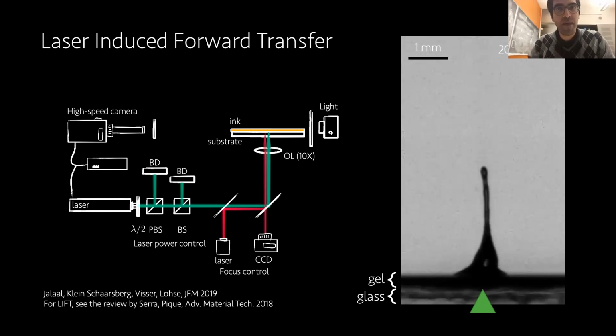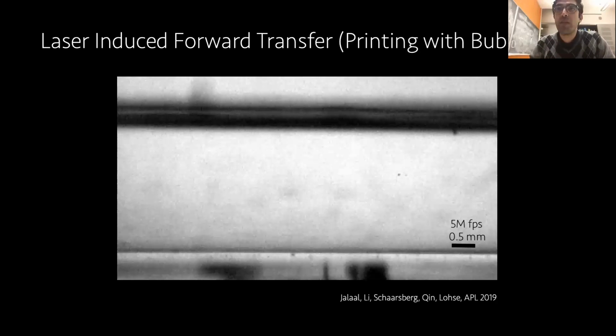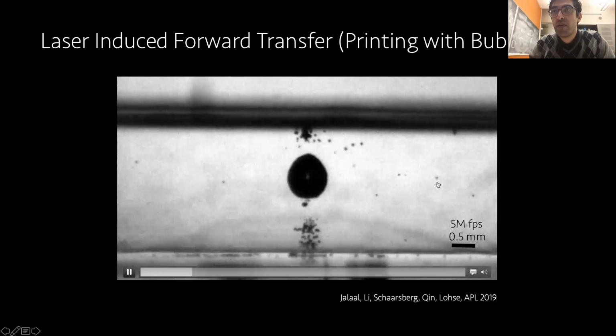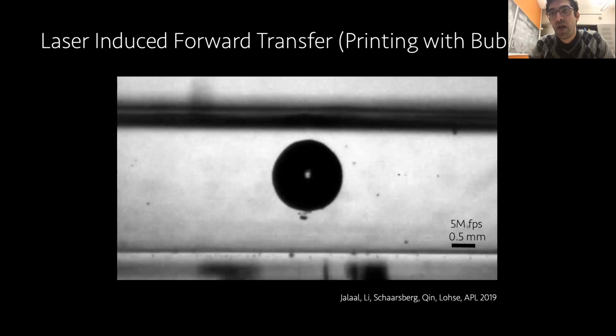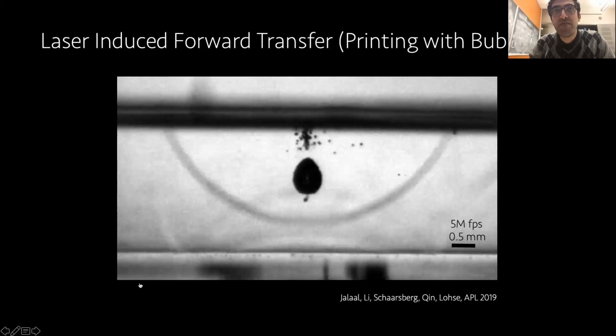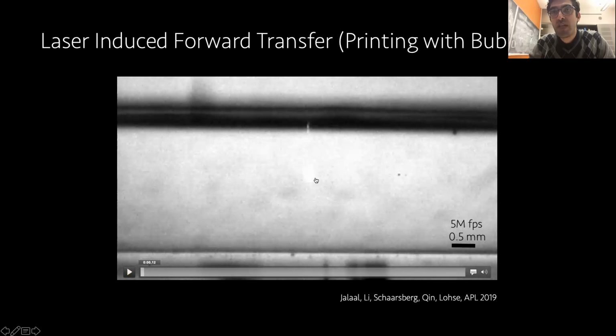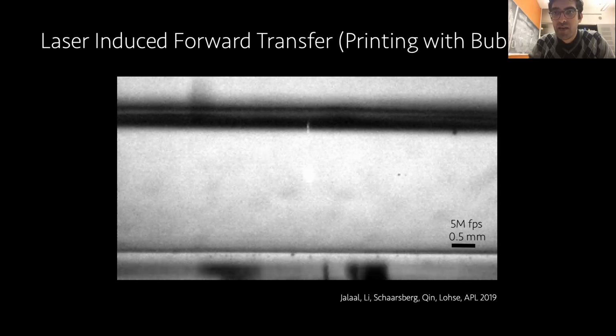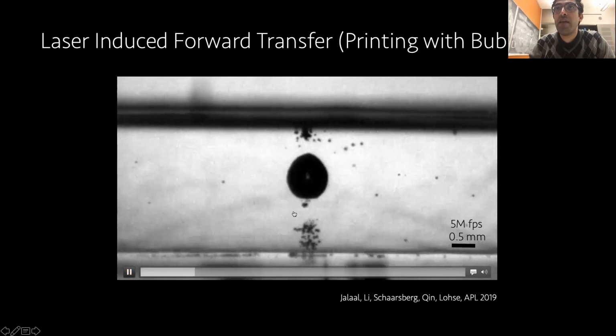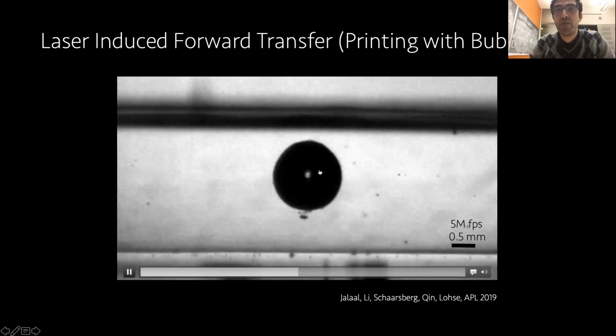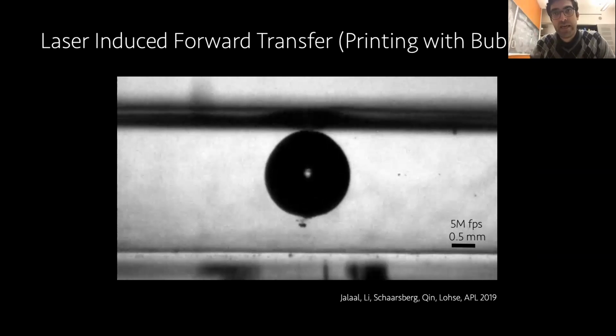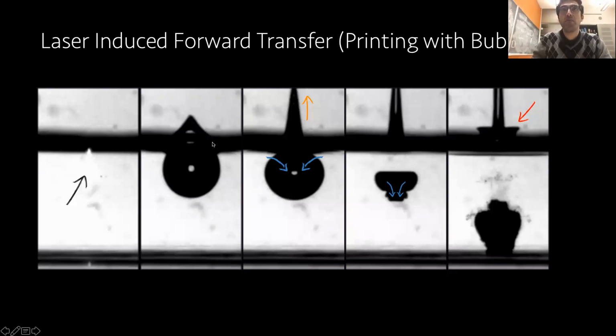One or two slides on how this system actually works. We, in fact, are printing with bubbles. When you focus a laser in a thin film of liquid, what happens is this. These are videos at 5 million frames per second, so this is a very, very fast process. What happened, and you probably missed, is at the very beginning, so I tried to stop the video. This bright spot is the plasma that you form. So you break the liquid thermally and optically. You form a bubble. It's a gas bubble that grows, and this bubble, from now on, controls the dynamics of the surface. Plasma forms, bubble grows, pushes the fluid on top, then the bubble collapses because of the pressure around it. And this whole phenomenon, which we explain in detail in some of our papers, forms this jet on the surface.